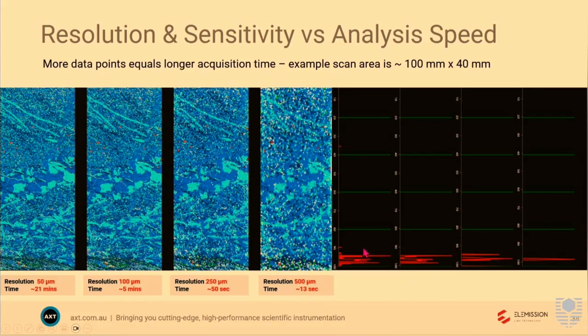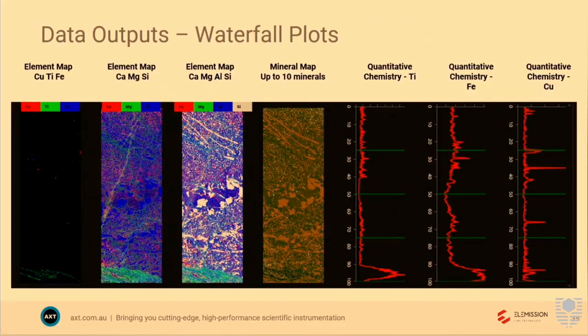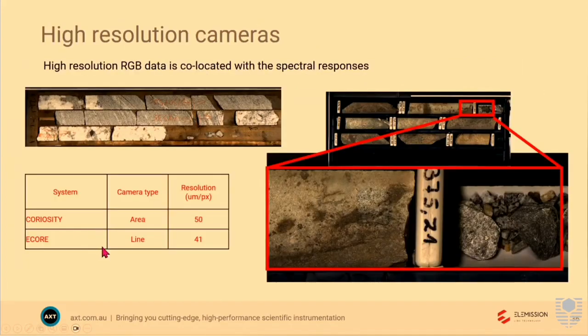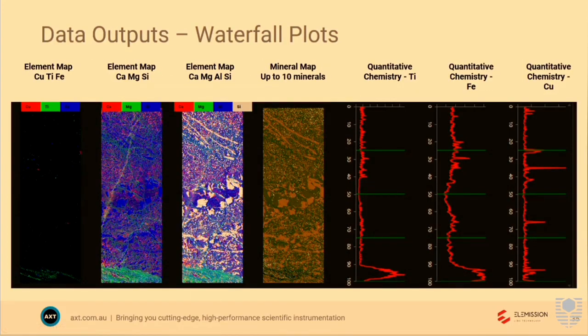These are peaks for silver. You can see there's a lot of activity for silver picked up at high resolution, but by the time you space it out to 500 micron resolution, you might well miss that silver. But an element is never there on its own, it's always associated with something else. If you look at these, it's exactly the same sample. You can see a lot of activity down here where that silver was. This is a 3-element map, copper, titanium, iron, another 3 elements, calcium, magnesium, silica, those 3 elements with aluminium thrown in, the mineralogy that's been applied, and then these are peak intensity lines for titanium, iron and copper. So the silver is associated with those.